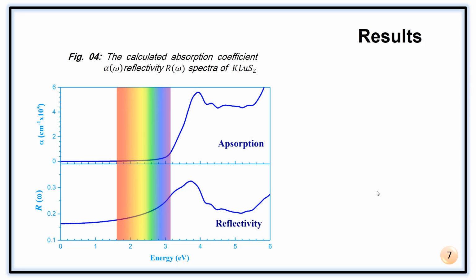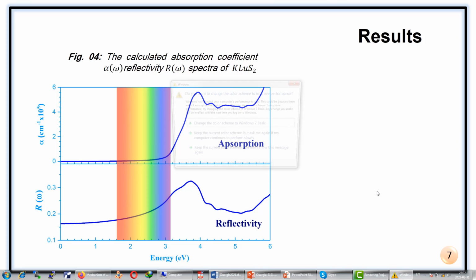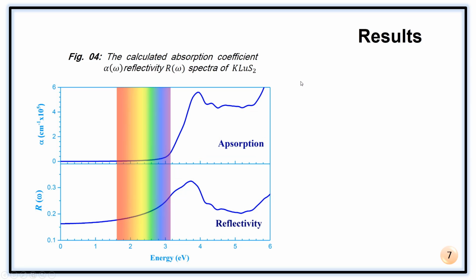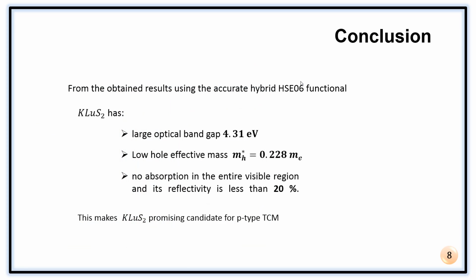Now I would like to turn to other important properties which can give information about transparency, the optical properties. As the figure shows, our studied material has no absorption in the entire visible region, and its reflectivity is less than 20%, indicating the high transparency to visible light for the studied material. In conclusion, potassium lutetium sulfide has a large band gap, small hole effective mass, and low reflectivity for the visible light. Therefore, this material is a promising candidate for P-type transparent conducting materials, TCM.